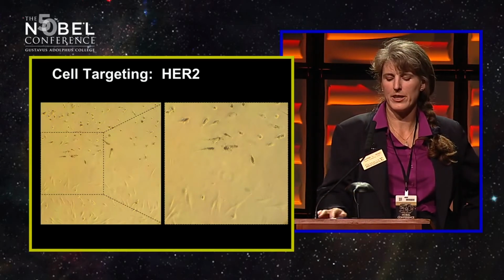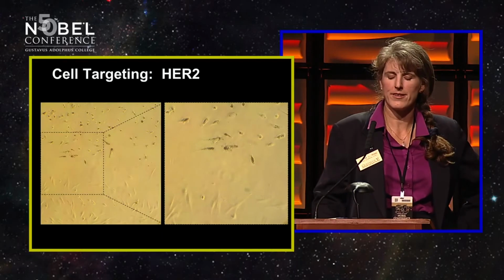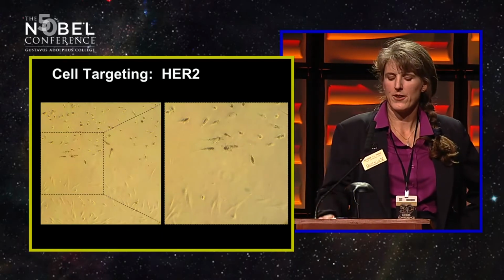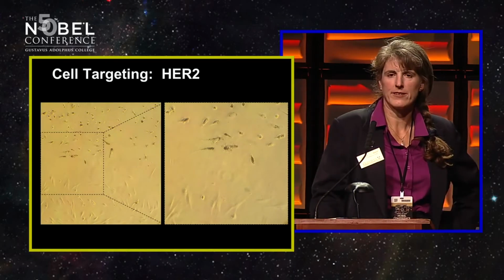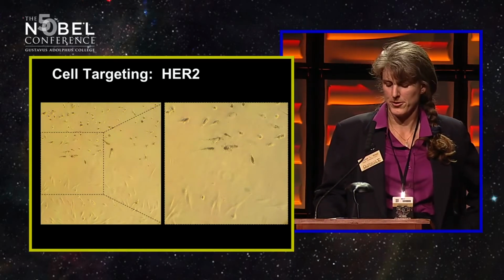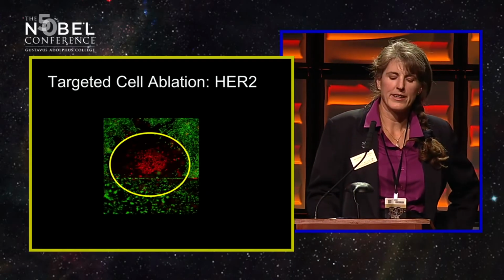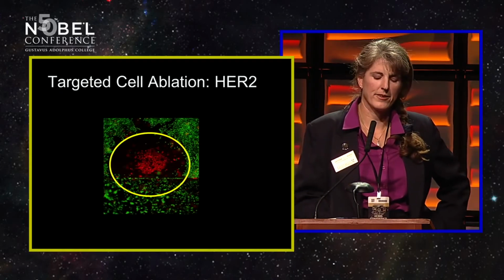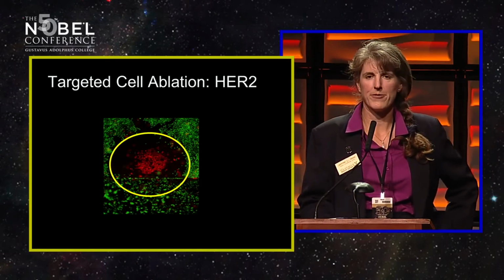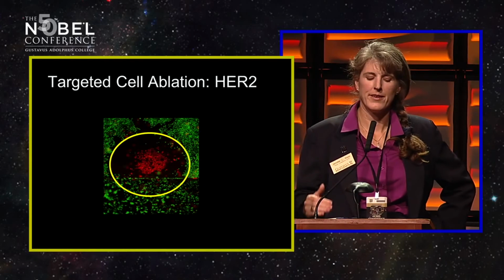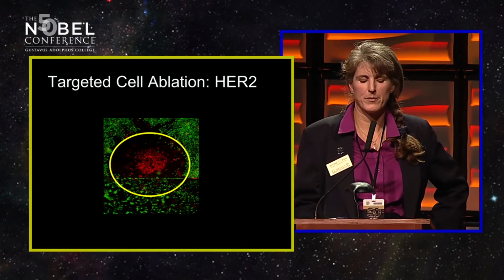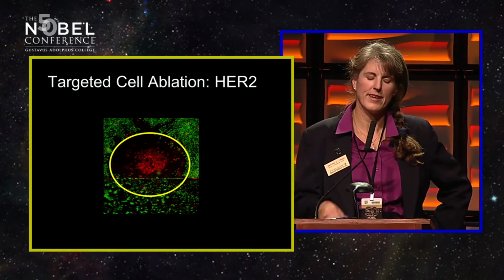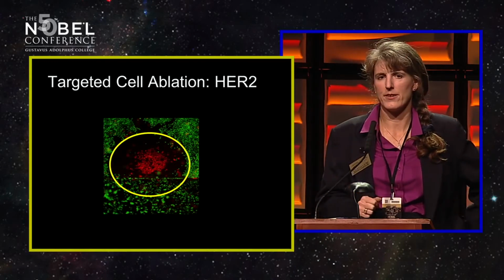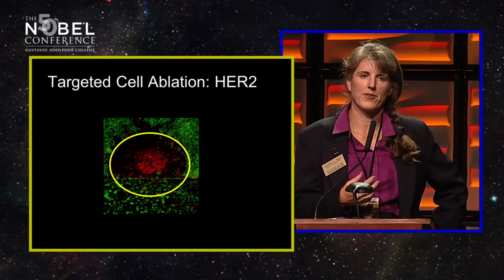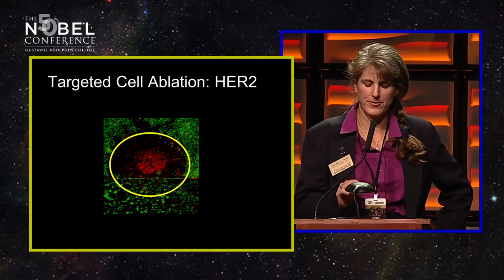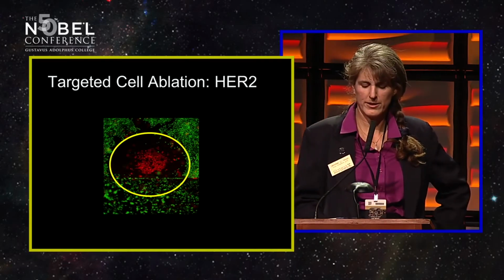And so at higher magnification to the right, you can see the dark staining where the nanoshells are present on the targeted tumor cells, but the immediately adjacent fibroblasts at the bottom show little to no binding of particles. And then if we expose those cells to an infrared laser, we see that we're able to very effectively kill the breast carcinoma cells that are above the interface, whereas the fibroblasts below the interface were unharmed by the process, and even fibroblasts that were immediately adjacent to a breast tumor cell were able to survive this process due to the specificity of the nanoparticle targeting and resultant heating.